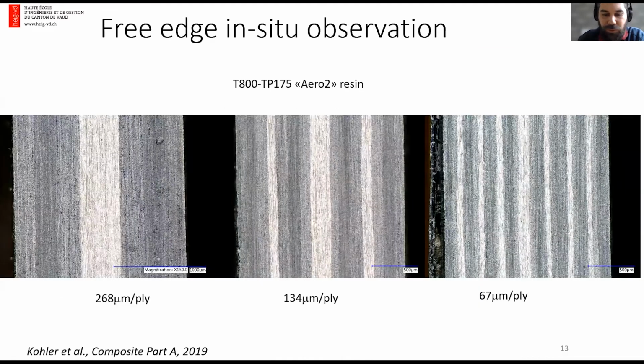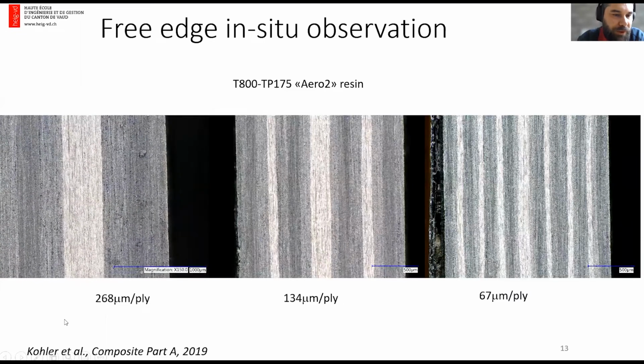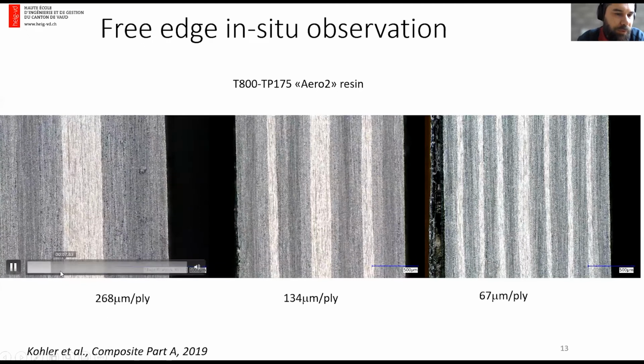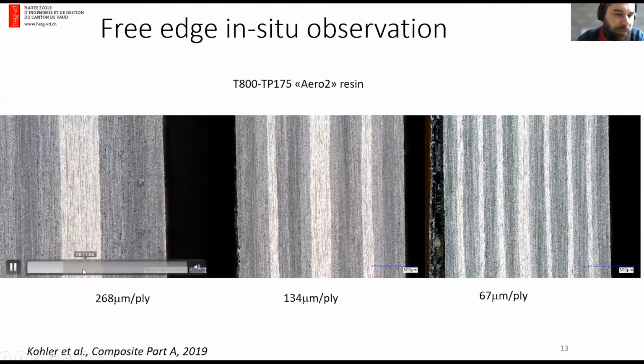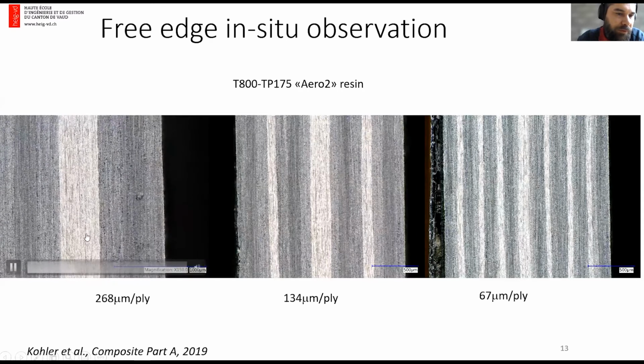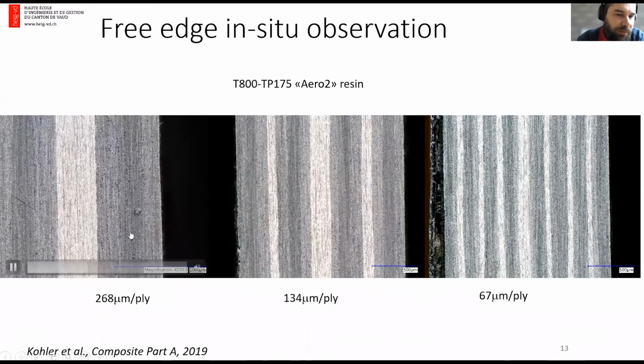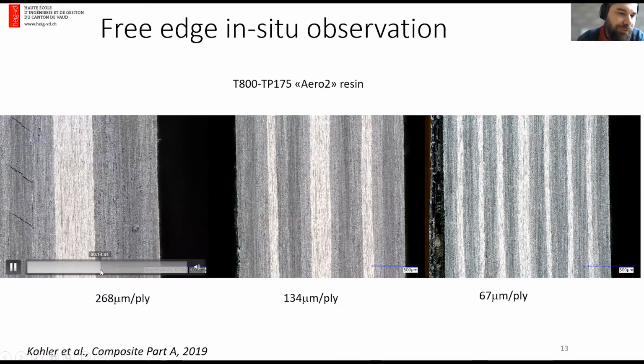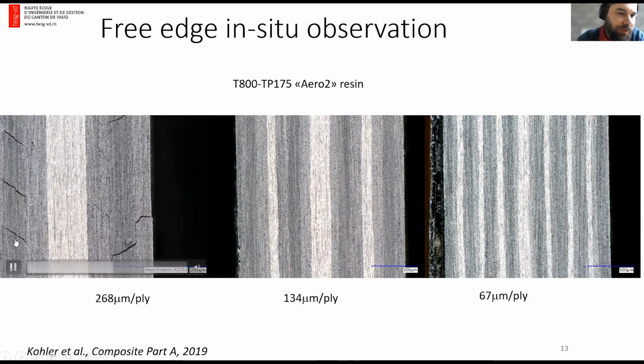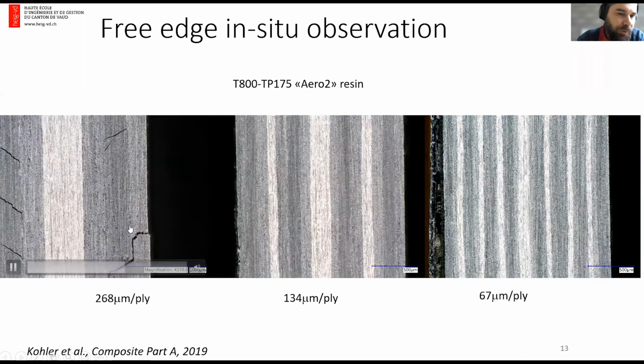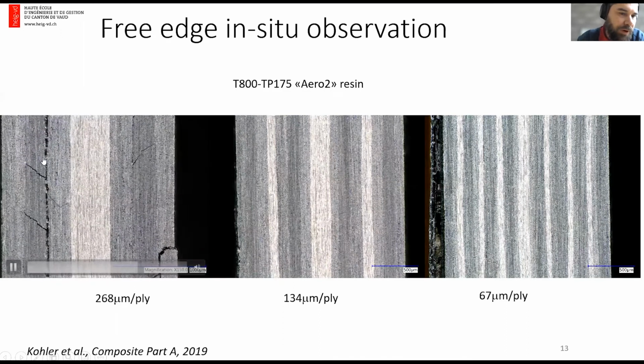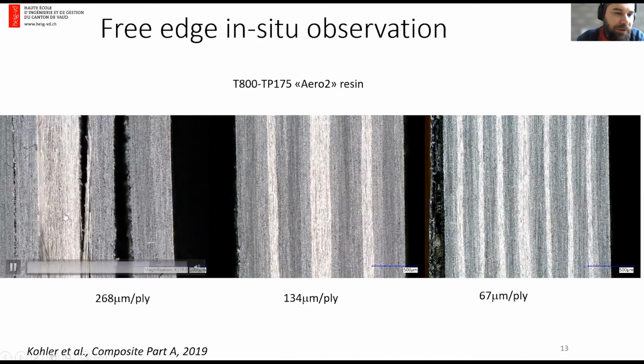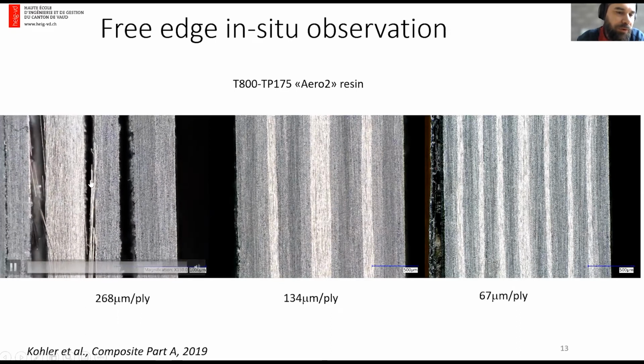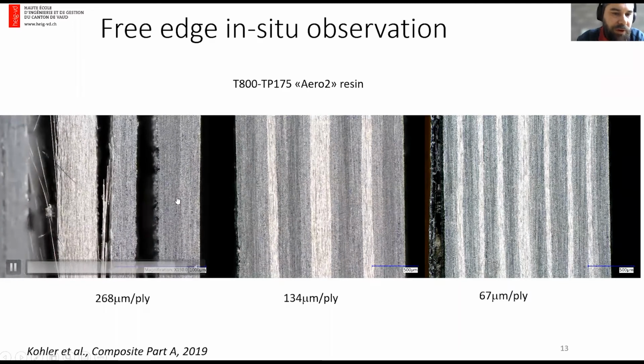But maybe to highlight what it looks like, here are a few videos. You can see here the free edge of a quasi-isotropic specimen during testing. Here a thick ply laminate where the 0° ply is in the center, and the 90 is here. So you can see at about 1/3, one half of the test, we have transverse cracks that very quickly migrate into delamination. And finally, a lot of delamination. And at the end of the test, only the 0° ply remains loaded.